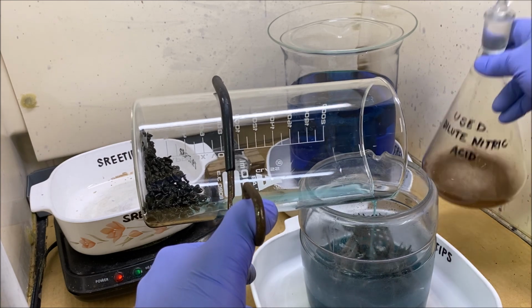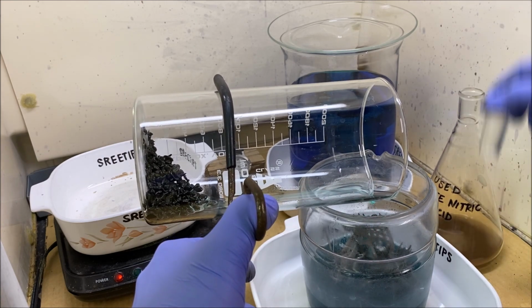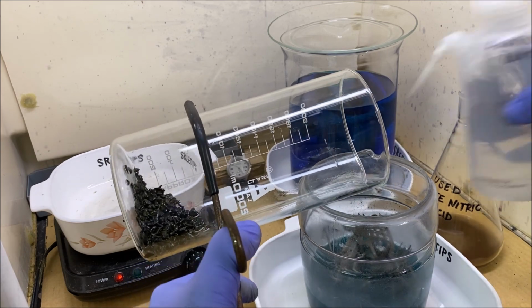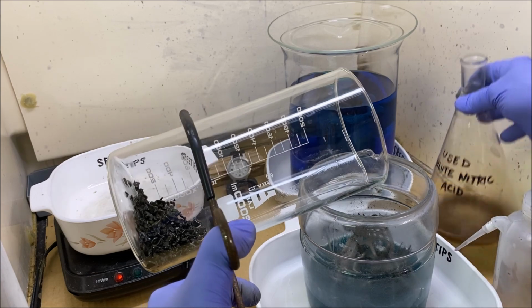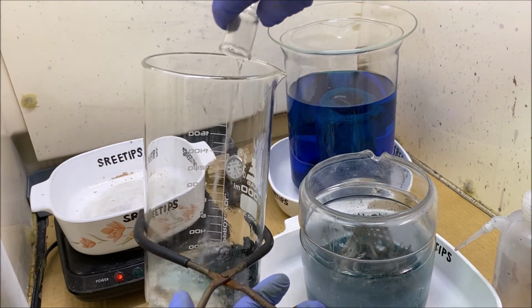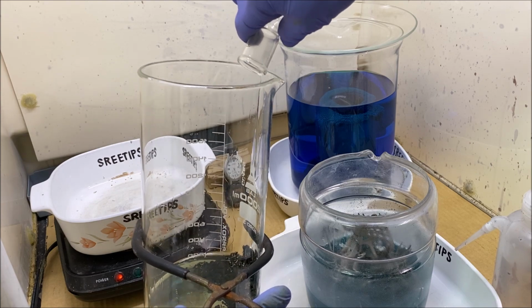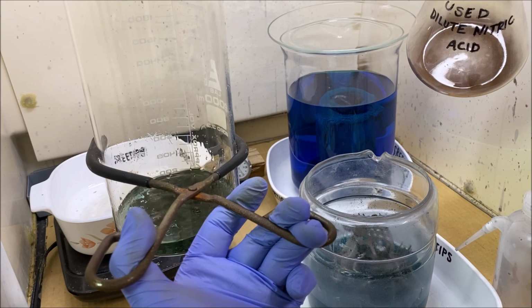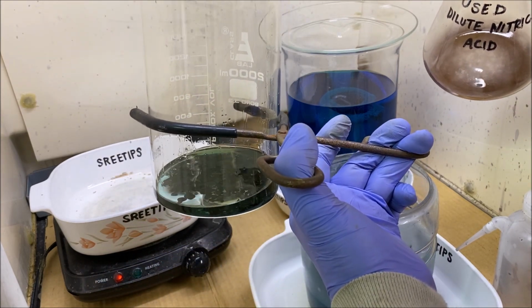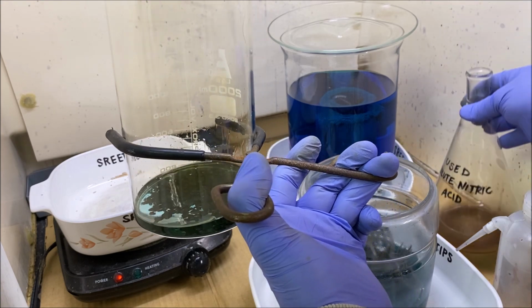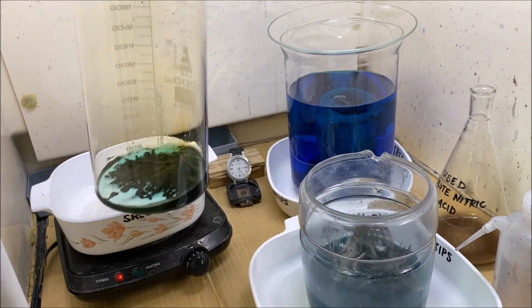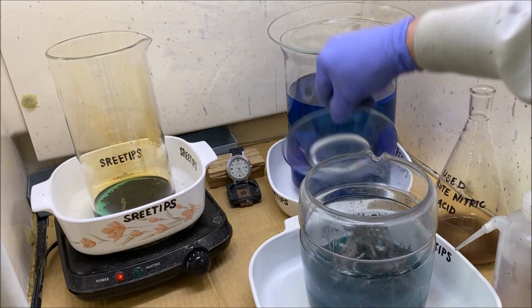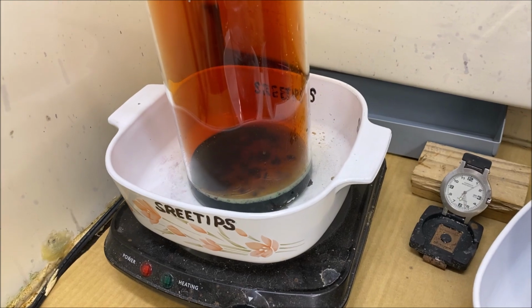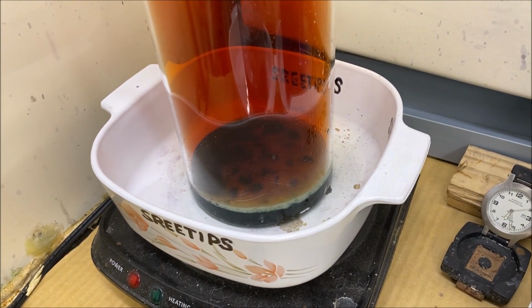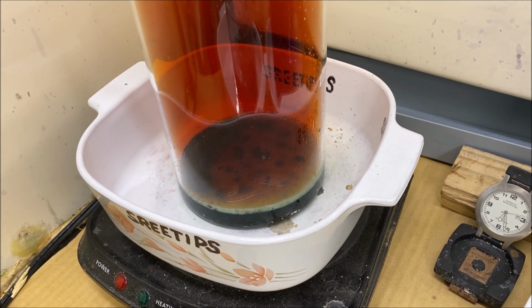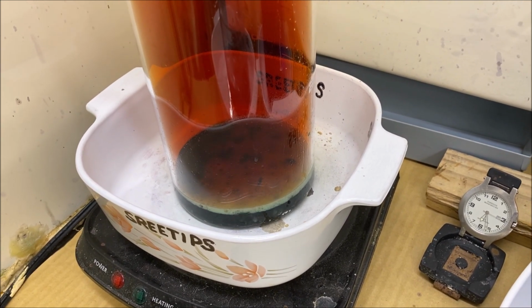I've got some nitric acid in this bottle. What I'll do is add this right on in. This is dilute nitric acid. And what I'm doing is I inquarted this gold with some sterling silver. Now I'm pulling the sterling silver back out with these nitric acid boils. Set this back up on the heat. Cover it up. Once I've pulled all the silver and base metals out of that gold, the gold gets left behind and it'll be high purity. There's about 3 troy ounces in that beaker.